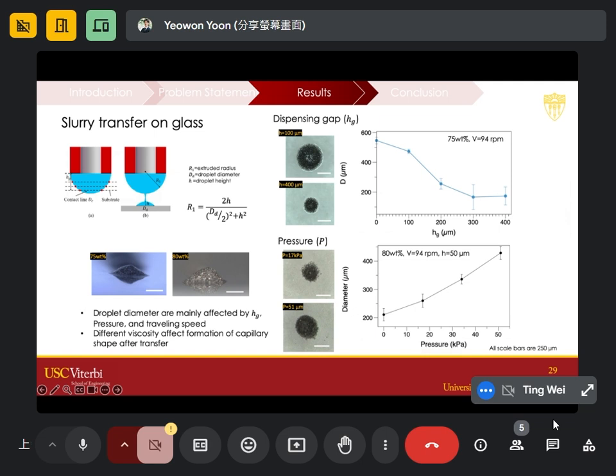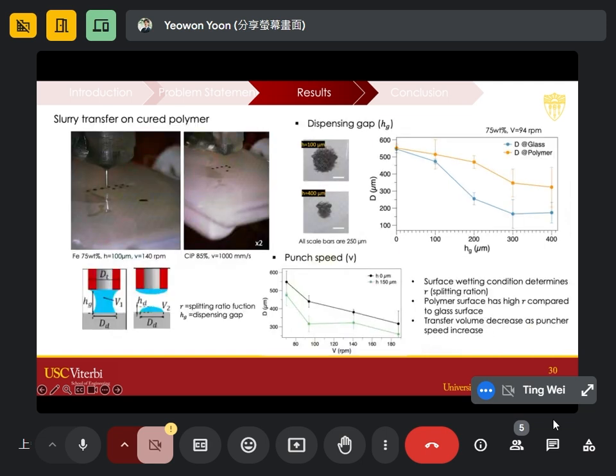So once we figure that out, we move on to hybrid printing, where we actually transfer slurries onto 3D printed parts. Here, a few things we can mention is the R, which is a splitting ratio function. That means the splitting ratio function differs by substrate. If you see on the right graph, increasing the printing gap ended up in different sizes of diameter, where the polymer substrate has a larger diameter, so the transfer ratio is a little bit larger than the glass. Punching speed also affects the printing, where the higher punching speed ended up in a smaller droplet size.